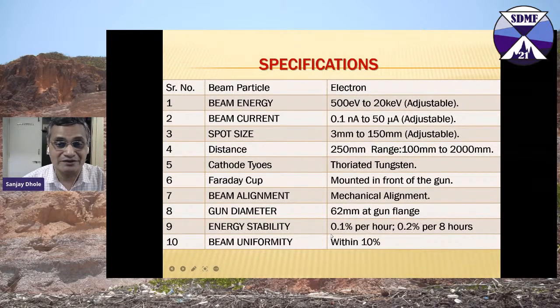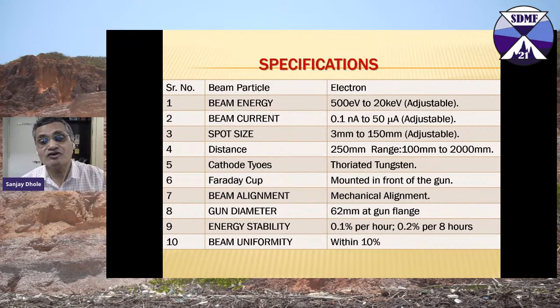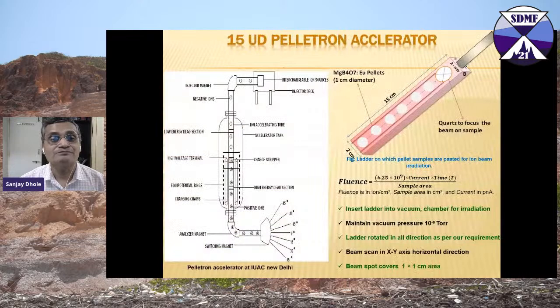This is quite acceptable. So even if you have a very large beam, you can put a sample at the corner, and it will receive the same dose as a sample kept at the center. There is a variation, maybe 10%, and that is quite acceptable as far as the dose is concerned.